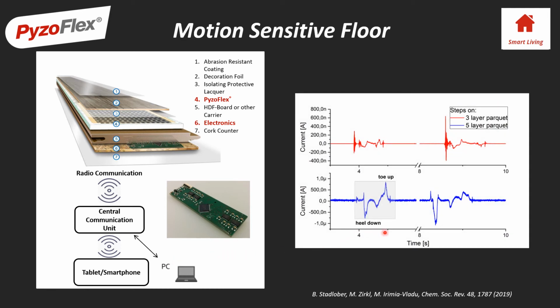And you can see a completely different signal form for lowering the heel, which is indicated as heel down here, or for lifting the toe, indicated as toe up here. The signals are especially pronounced and reproducible for the softer 5-layer parquet.